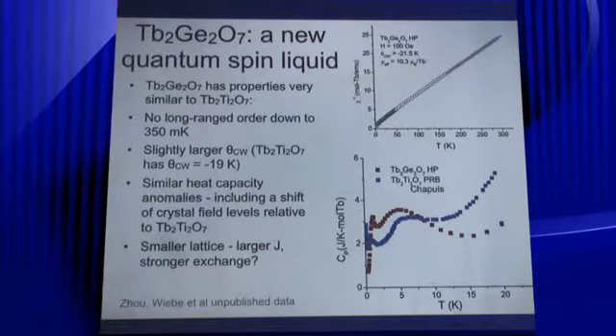So the crystal fields are shifted due to the different exchange that you have in this compound. So small lattice, larger J, stronger exchange, and the crystal field, this one shifted down a bit, and this one shifted upwards a bit with respect to terbium titanate. But when we start measuring these compounds, we're trying to get enough neutron scattering, but it's going to take a postdoc a while. He's going to tear his hair out.